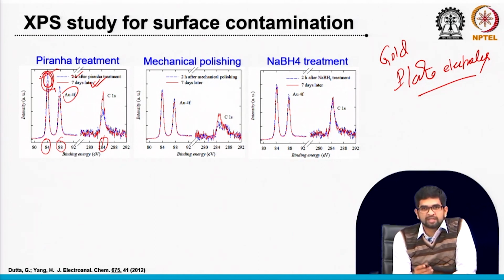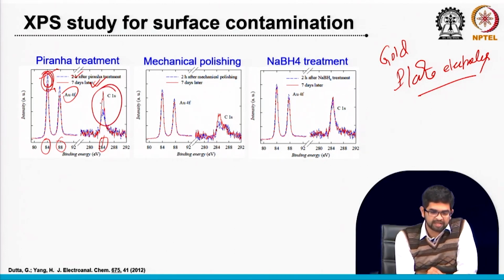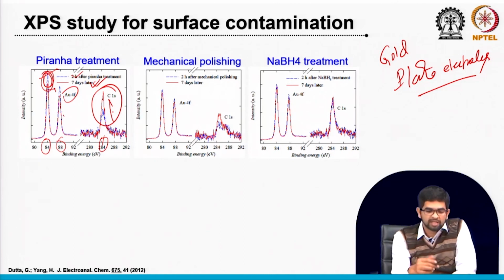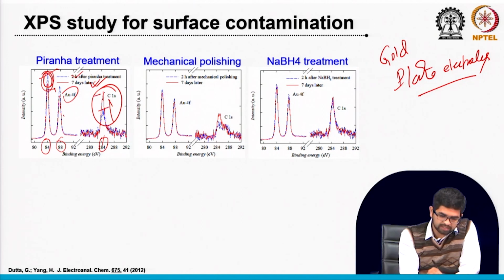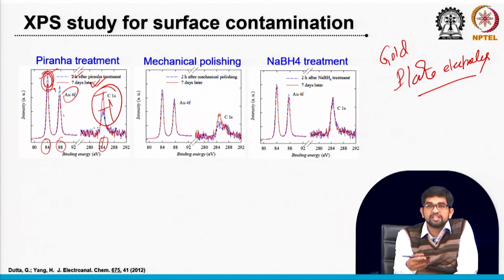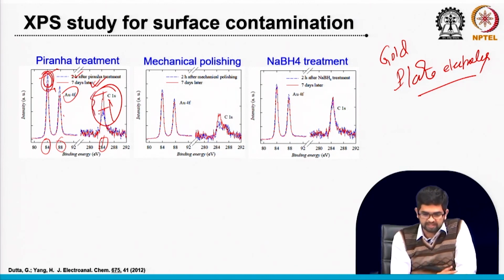That contamination means generally the organic contamination, which we are thinking of. So we checked the carbon contamination. You see here the carbon contamination peak after 7 days. See, the gold peak decreases, but the carbon peak increases. Why? Because gold can be covered with some carbon contaminant, so the gold peak should decrease, and the carbon peak after 7 days should increase, because the carbon amount is increasing. So you can see this much amount means increasing. So a little bit of contamination is there, that we can tell from this X-ray study.